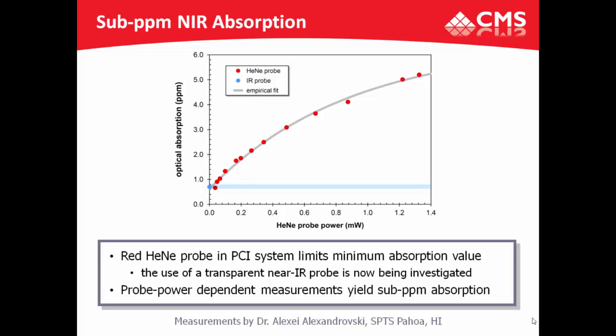This is measured using the photothermal common path interferometry technique. You have a strong pump beam incident on your coating. The pump beam is chopped, or time modulated, and forms a time modulated thermal lens. You also pass a probe that measures the phase of the thermal lens. You rely on the fact that the coating is a thin film compared to your bulk substrate, and you just need to know the thermal properties of the substrate.